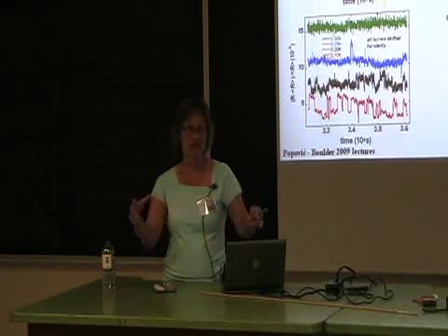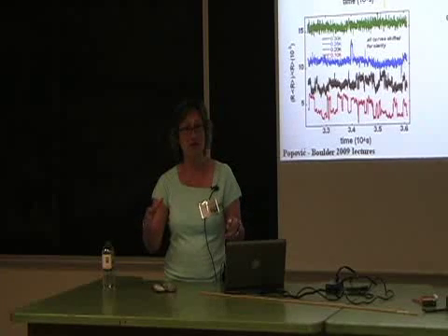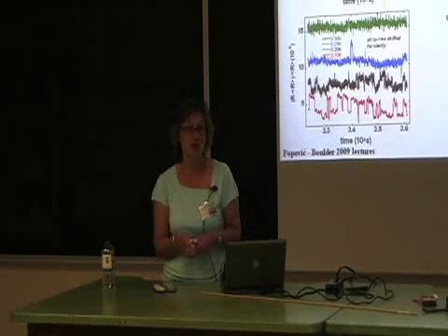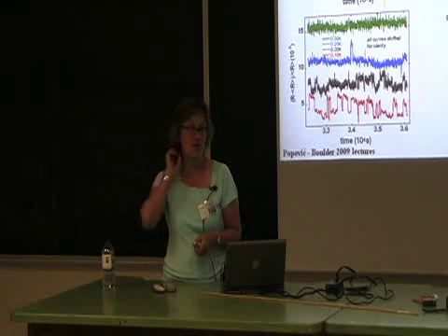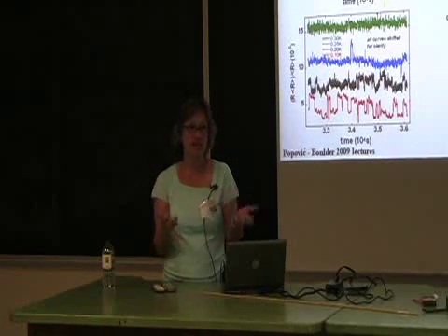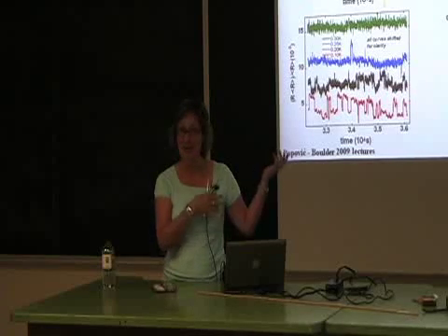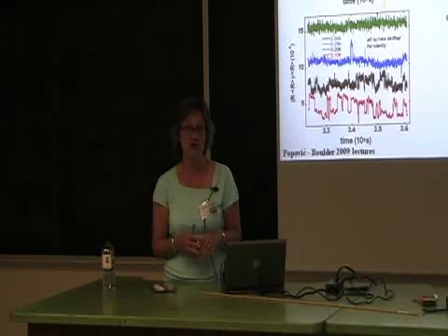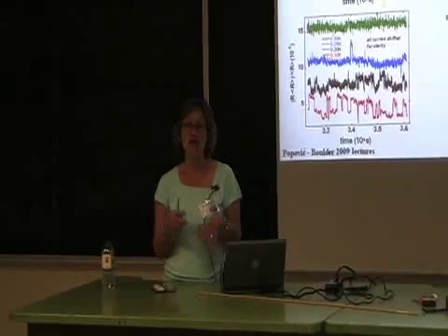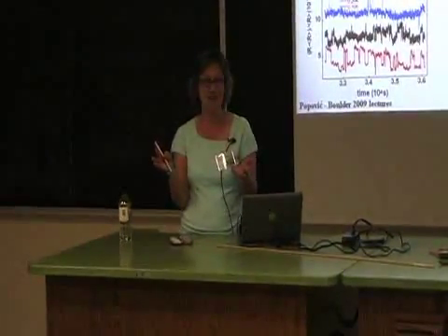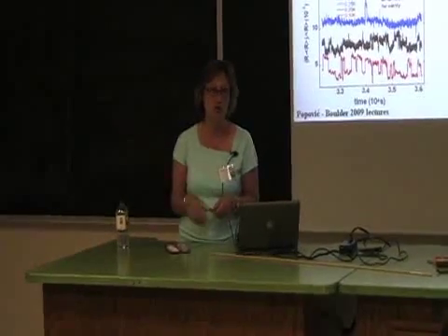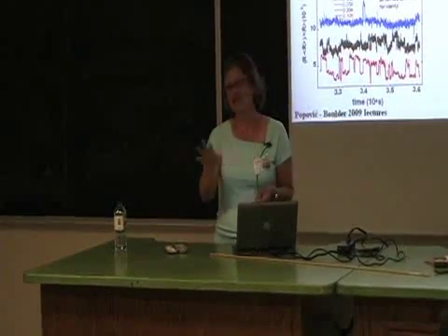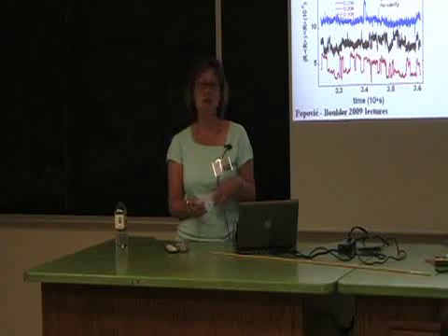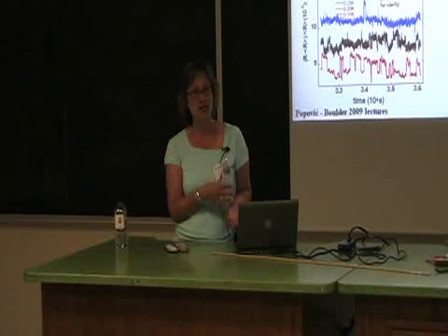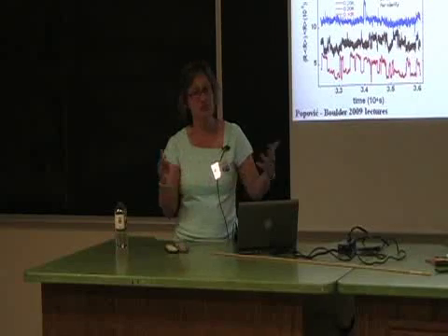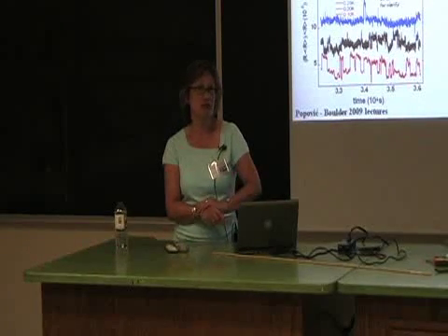For example, with these STM pictures, people do it over a fixed period of time. But I'm pretty sure they will try to do it also at lower temperatures. Maybe they will see some dynamics. The NMR people like this because they've been seeing these dynamic inhomogeneities for a long time, but at much higher temperatures. But people always criticize one another. Like these are local probes, so they say, oh, it's a local probe. That's STM, oh, that's a surface probe. It's no good. So it's good to have some complementary probes. Like this is a bulk probe. It's something on different time scales. So it's good. Yeah.